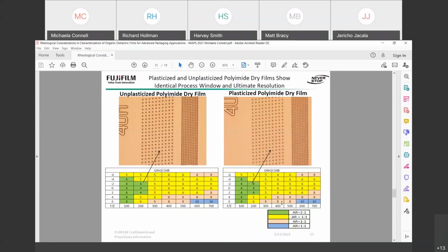So next, this is the imaging performance. As you can see, the ultimate resolution was identical in the focus exposure matrix, and both the plasticized and unplasticized films show a 2-to-1 aspect ratio at the best doses and focuses.